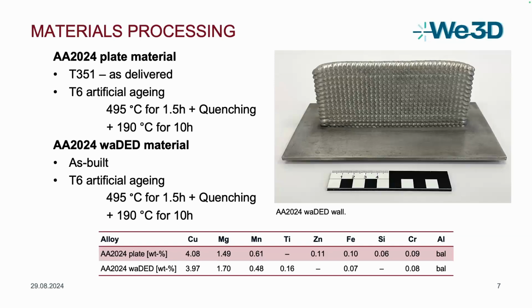The materials in the study: we used 2024 plate material T351 as delivered as the reference material, then also in the T6 artificial aging condition, which includes solution heat treatment, quenching, and artificial aging. Furthermore, the 2024 wire arc DED material in the as-built condition and in the same T6 artificial aging condition. And here we have such a 2024 wire DED wall.